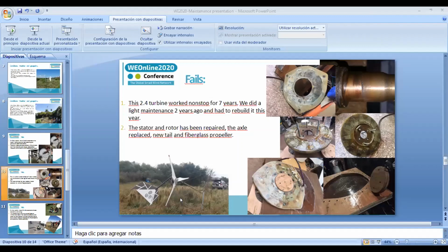Can you hear me? I might ask a question because I had an issue with the turbine that is quite common, I think. Some of the magnet steel discs were rusting, and the rust sneaks underneath the resin and pushes the resin away from the steel disc and the magnet. The issue was basically the steel disc starting to rust, and somehow water makes its way behind the resin casting on the steel disc. Once that happens, it's basically a full repair: you have to replace the magnet disc and put the magnets on again. I wonder if anybody else had experience with such failures and what they did about it, because from this project I started only using galvanized steel discs. Maybe someone else has experienced something similar. Just asking.